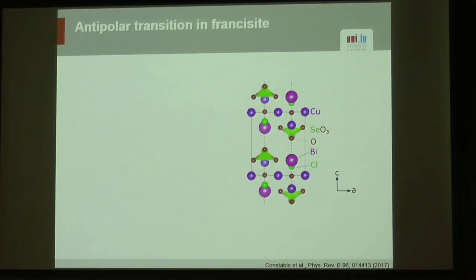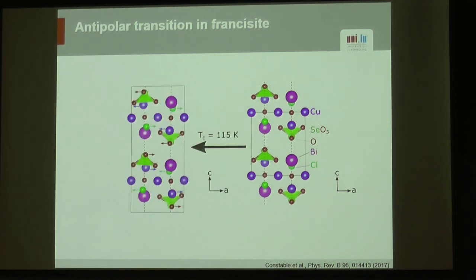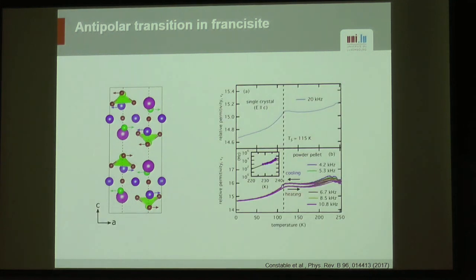So here is, again, the crystal structure as seen along the B direction. And what you see here is you have some antiparallel displacements of a number of ions. So this is chlorine, copper, and a bit of oxygen here. So this looks very nice because we have antiparallel displacements, and also it's completely one-dimensional. So this is the main difference with what you would have with the perovskites typically.